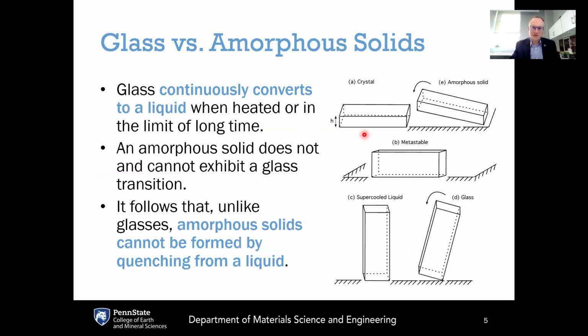So how is this different from amorphous solids? A glass continuously converts to a liquid either when heated or if you wait in the limit of long time. On the other hand, an amorphous solid does not and cannot exhibit a glass transition because the structure of an amorphous solid is very different from that of the liquid state. It follows that, unlike glasses, amorphous solids cannot be formed by quenching from a liquid.